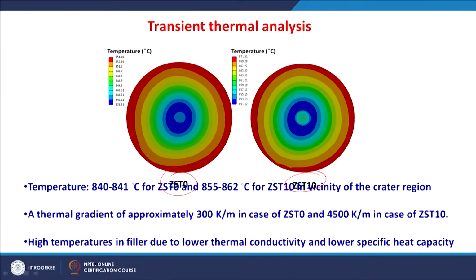We can see this is the sample of ZS T0, this is ZS T10. Now, you see the temperature distribution here. For ZS T0, the temperature interval you can see here is from around 840 to 841 in the vicinity of this crater region. Whereas for ZS T10, in the vicinity of the crater region, the temperature interval is between 855 and 862. So, a thermal gradient of approximately 300 Kelvin per meter in case of ZS T0 and 4500 Kelvin per meter in case of ZS T10 were observed.